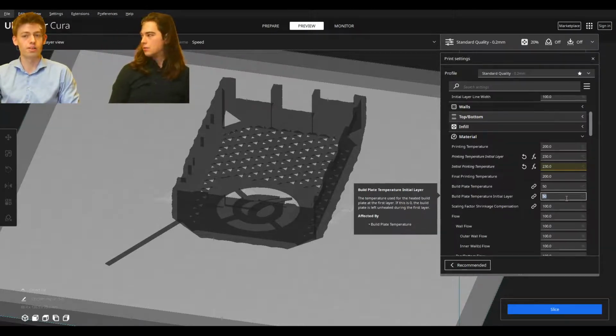And there could even be steady state error. So even if you let your bed sit for 10 minutes, the bottom can still be 65 and the top can still be 60. That can still happen. It's called thermal resistance. So glass is a very good insulator, and it's hard for heat to go through it. So once it's heated up, it'll stay at temperature pretty easily.